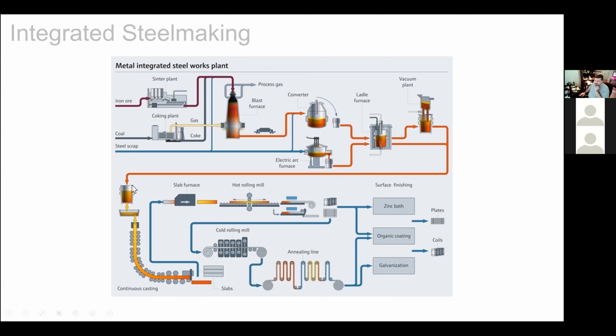And at the caster, we basically allow the steel to pour out of the ladle into a big trough. And that trough feeds water-cooled copper molds that help to solidify the steel into a particular shape. And the steel is cast continuously. So as it moves through to this point where it's cut off into specific lengths, the liquid core of the steel is solidifying.